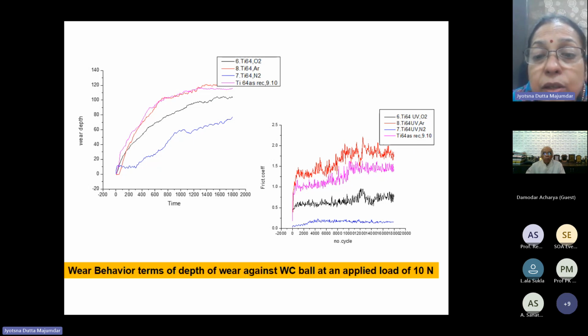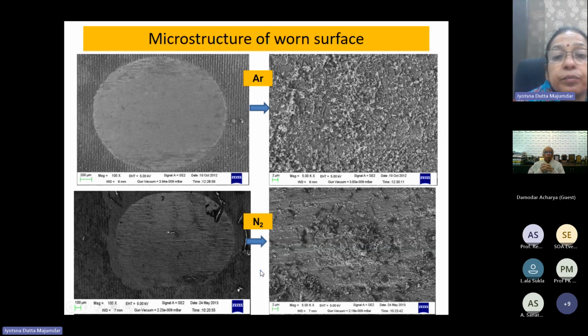So these days we are not doing any dry wear study. We are trying to understand the performance of the coated material by tribocorrosion, where we are doing the same fretting wear in presence of the Hank's solution. But we are getting more or less similar trend. Whatever we get in dry wear, similar trend is observed in wet wear as well. But obviously, the corrosion effect is also combined in wear. So that's also very good information on how the materials behave in real environment.